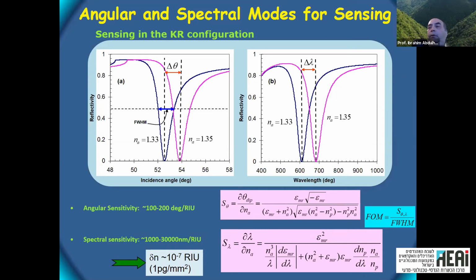And if we calculate easily what will be the minimum refractive index that we can measure, we can estimate that quite easily, depending, of course, on the noise of the system. But typical systems can go down to 10 to minus 6, and even with some care could be 10 to minus 7 RIU, which corresponds to 1 picogram of material per unit area of millimeter square. That's very small. In terms of concentrations, it's like 0.1 nanograms per milliliter or even less.